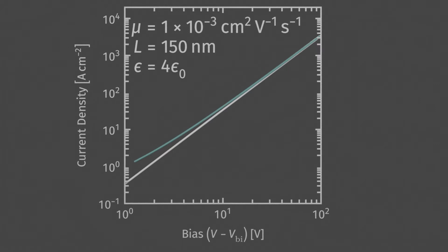while full drift diffusion simulations show the same behavior after the space charge set up by the bias exceeds the background levels. This mobility is higher than is typical for an organic, but under these high field and carrier concentrations, a higher mobility results in these disordered systems. This relationship is the result of simulating with a Gaussian disorder mobility model. And putting the average mobility back into the analytic treatment, the underlying behavior is still captured. But the accuracy of these predictions requires using a mobility model congruent with lasing conditions.